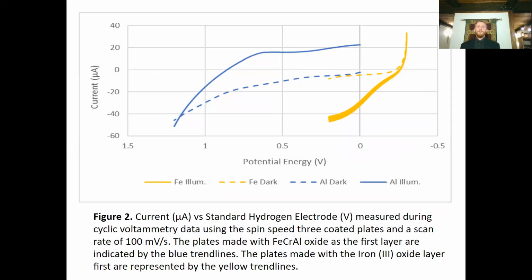Formation of the all-metal-oxide PN homojunction was confirmed by differential short-circuit current values measured by cyclic voltammetry. The measured short-circuit current values were found to correlate with different intensities of light as the plates were illuminated. The current voltage curves of the plates in a 0.1 molar sodium hydroxide solution indicated that the sequentially processed plates exhibited photocurrent. The current voltage curves are represented by figure 2.